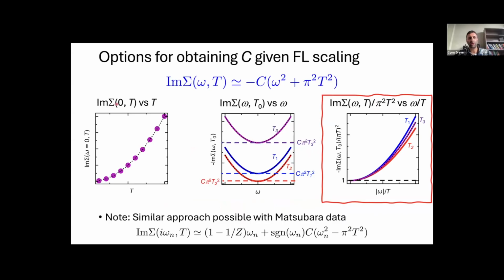And therefore, we can get away from just looking at the zero frequency point of the self-energy, and we can fit the full frequency dependence. And as I'll show, that gives us a much more robust calculation of C and therefore the resistivity. Specifically, if we plot imaginary part of sigma over pi squared T squared versus omega over T, then the scaling relation basically means that all the calculations at different temperatures should collapse to the same curve. And we can also do this on the Matsubara axis, as I'll show in a few slides.